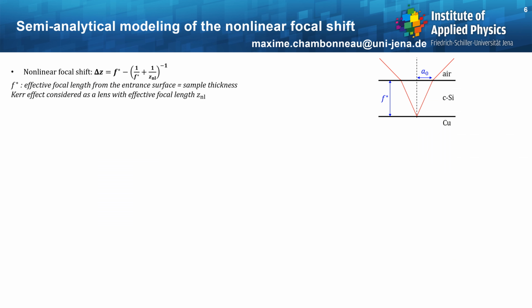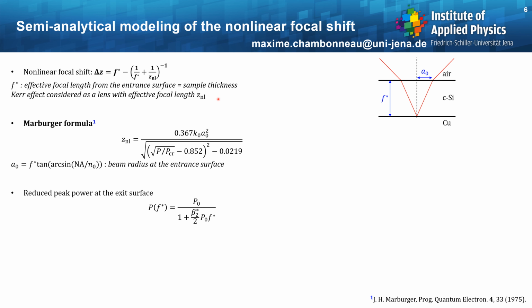In order to predict the behavior of the nonlinear focal shift as a function of the input pulse energy, we have developed a semi-analytical model. This model relies on this equation here, where delta Z corresponds to the nonlinear focal shift, F star corresponds to the sample thickness, and ZNL, NL for nonlinear, corresponds to the effective focal length associated with Kerr effect, which is considered as a lens. Then one can determine the value of ZNL by using Marburger formula, which is shown here, where K0 is the wave number, A0 is the beam radius at the entrance surface, PCR is the critical power for self-focusing, which is a first fitting parameter, and P is the reduced peak power at the exit surface, which is defined as follows.